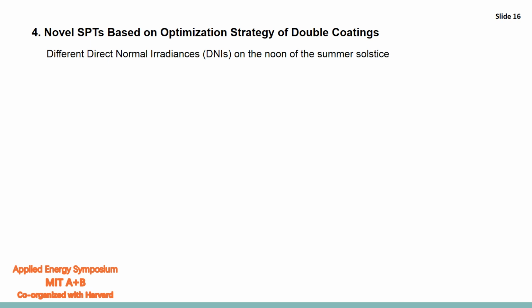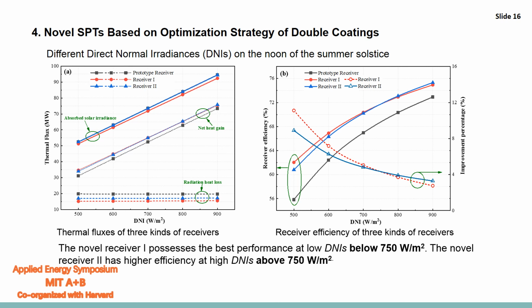The thermal performance of the novel receivers under different direct normal irradiance, DNI, is also investigated. It can be seen that the two kinds of novel receivers achieved superior thermal performance at DNI from 500 to 900 watts per meter square, and the largest increase is achieved at the lower DNI of 500 watts per meter square, where the receiver efficiencies are enhanced by 11 and 9% compared with the prototype receiver. Besides, novel receiver 1 possesses the best performance at low DNIs below 750 watts per meter square, and novel receiver 2 has a higher efficiency at high DNIs above 750 watts per meter square.